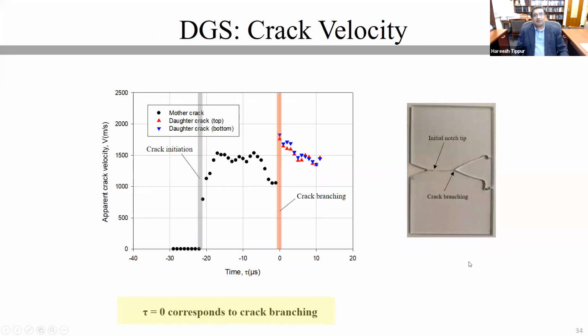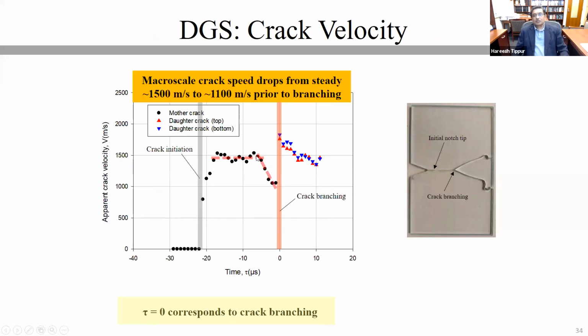Crack velocities can be easily backed out from these measurements. Crack velocity once again jumps to about 1500 meters per second, as in the photoelasticity experiment. Then it begins to slow down. As I mentioned previously, slowing down is a consistent indicator of the crack branching that is about to happen, and it branches. Then it reaches 1700, 1800 meters per second, and then settles back into a lower velocity of 1500 again. It doesn't drop all the way back because the crack has already approached the edge of the specimen, and it cannot branch at a velocity as high as 1500 meters per second. So the observation is that it has to slow down for it to branch. I will explain why that is the case later on when we talk about fractography.